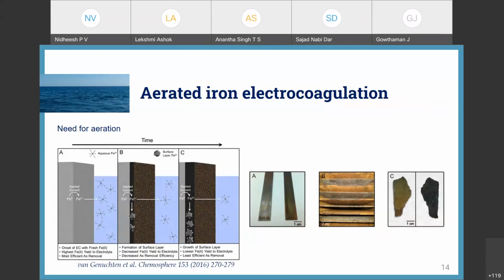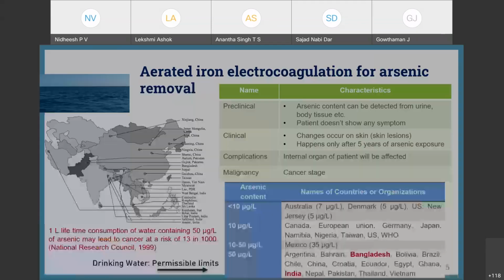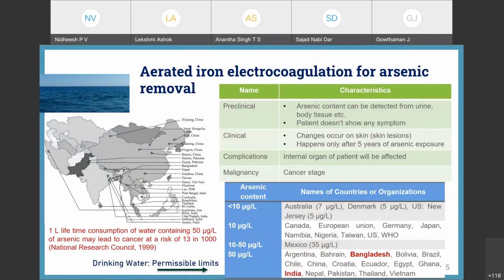Studies have found that the rate of magnetite formation is very high because of the very low oxygen content. So that's why we started working on aerated iron electrocoagulation, and fortunately we got some good results in comparison with the basic electrocoagulation process. Now we are targeting the removal of arsenic from water by aerated iron electrocoagulation.